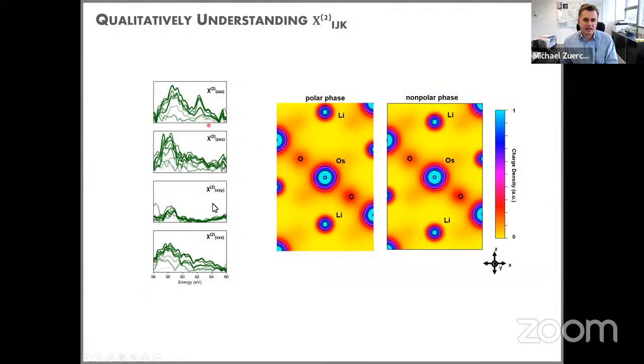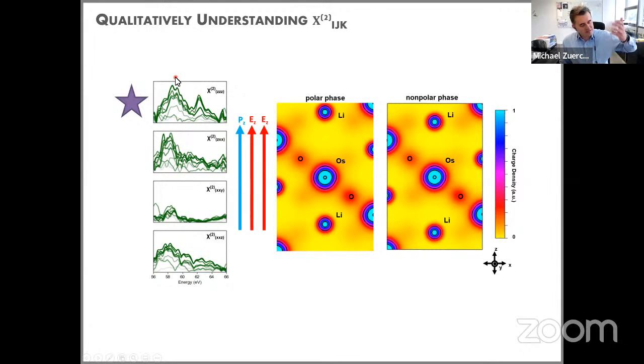So if we look at these calculated Chi2 spectra, what I show here is the projection of the crystal and its charge density into the CX plane. Okay, so this is the CX plane of the crystal. And just for orientation, I marked the different atoms in here. So osmium in the center. For the polar phase, we see lithium is slightly displaced with respect to the center. So we have a polar phase. Now we can look, for example, at what chi CCC really means in this case. If this is the C-axis, this means that we have 2 electric field components of the driving field and the polarization in the same direction. So basically, all the polarization is pointing along the polar axis. In this case, we see the second harmonic is absolutely maximized because we are probing along the direction of this polar axis.